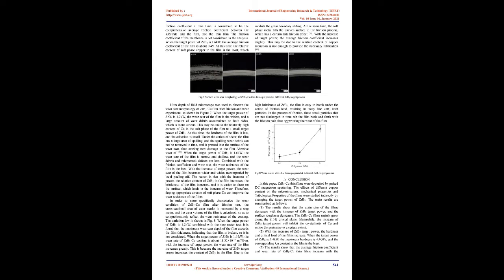With the increase of target power, the hardness and elastic modulus of the films increase non-linearly, reaching the maximum at 2.4 kilowatts, which are 4.4 GPa and 185 GPa, respectively. The reason may be that the target power increases the bombardment intensity of the film, and more B elements are splashed out to form strong covalent B-B bonds, which increases the hardness of the film.